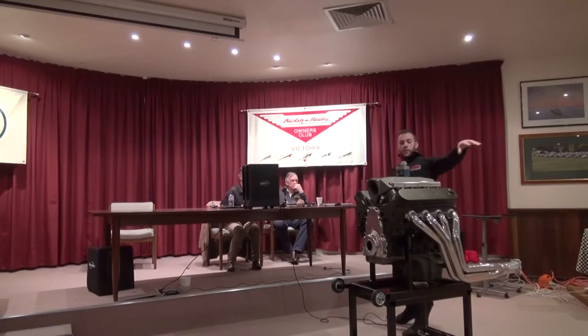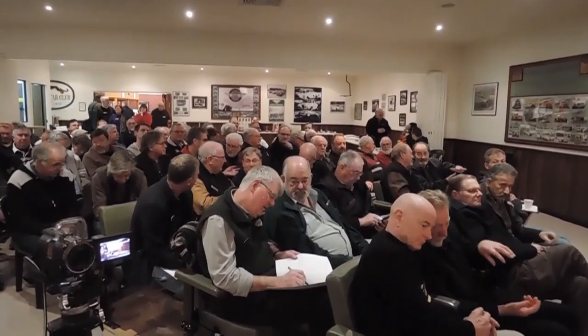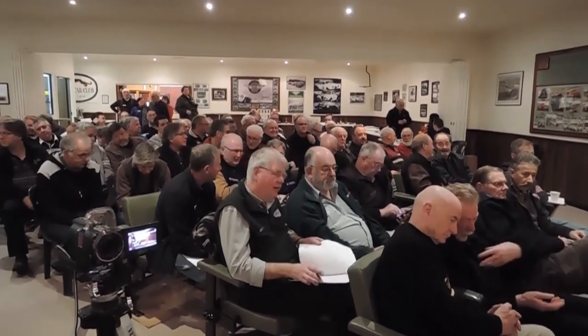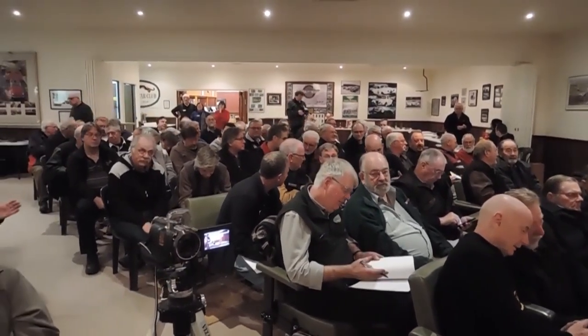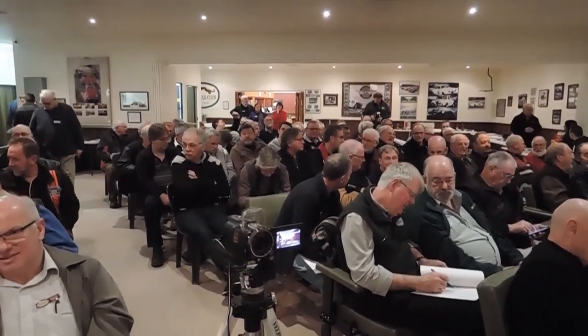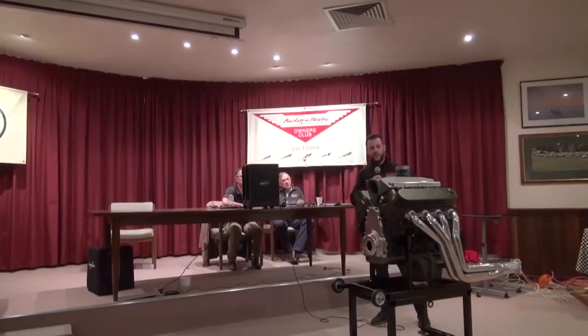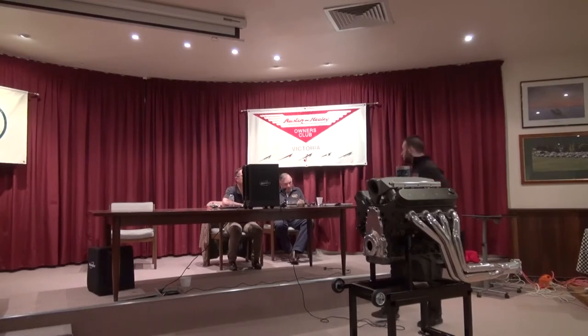Engine builders all around Melbourne call me every day. I'll give you a bit of an understanding: you can get a build-up of either 1, 2 or 3 on saving a set of pistons, and that's probably the best thing, if they're a rare piston and you want to reuse them, we can give you a build-up so then you can remachine your block. But not only that, the friction. We've actually had dynos back-to-back, one without coating and one with coating, and you could actually hear the difference, how smooth the sound of that engine was with the coating than it was without. So it does work quite well.